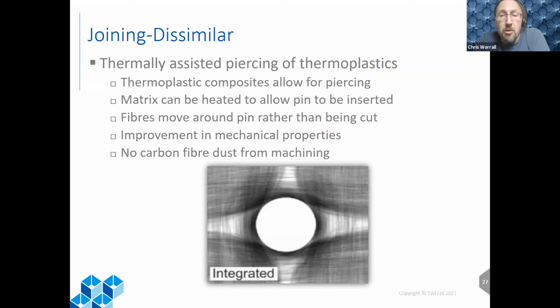And it can also be used to recover a hole if it's made in the wrong place or it needs to be repaired or removed. Then the elastic strain energy in these fibers, if we reheat it again, then they will return to their original position. And with the addition of a little bit of extra polymer, we can fill the hole in and you'd never know it was there in the first place.